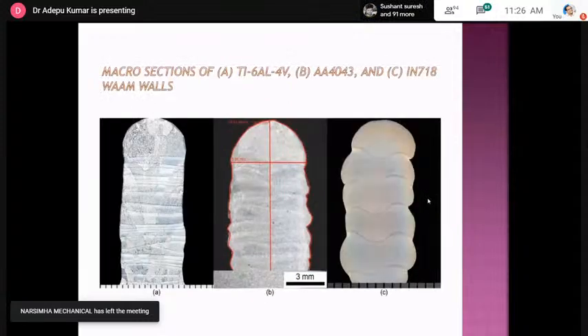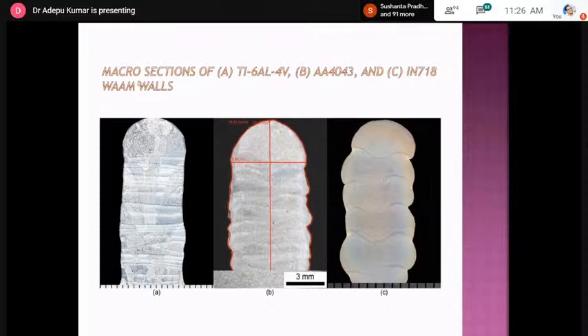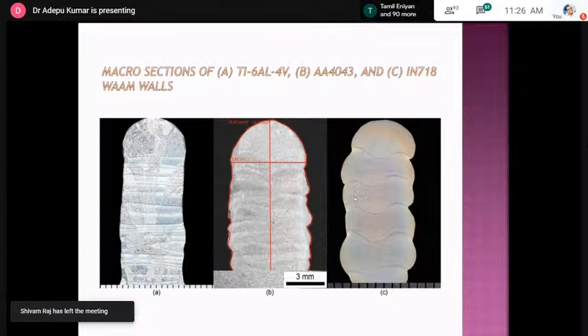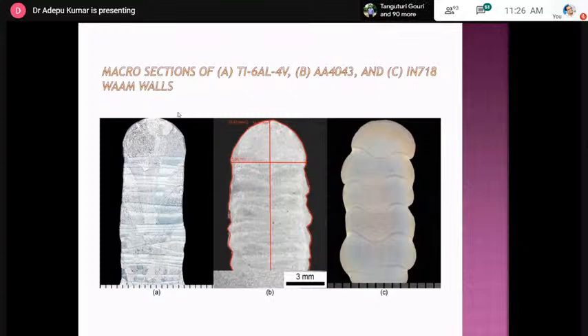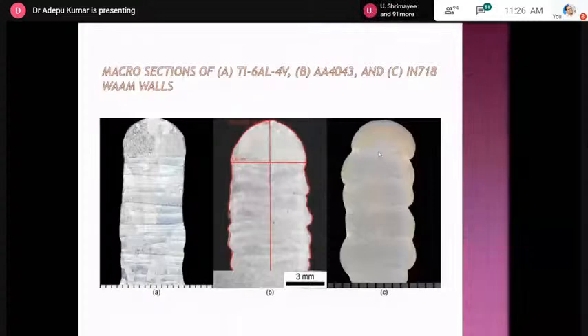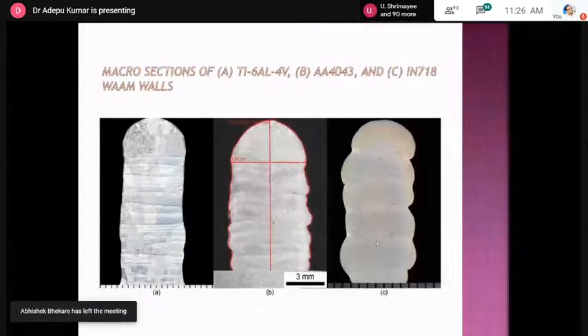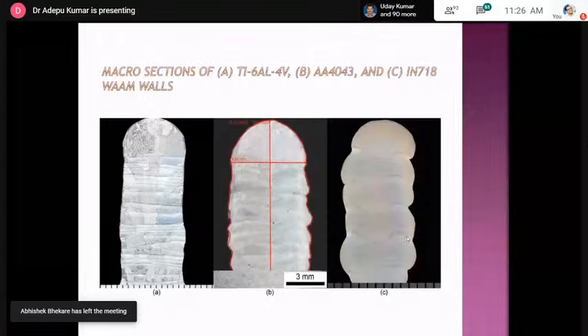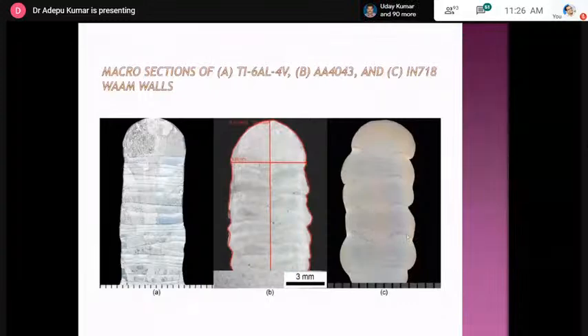So for the benefit of the participants, I am sharing some microstructures of various materials made by the wire arc additive manufacturing process. The first one is titanium 6Al4V, then 4043 and Inconel 718. Just see Inconel 718, you can find layer by layer. This is one layer, another layer, another layer. In between the layers, there is an interface. We can call that interface a metallurgical bond between the two layers.